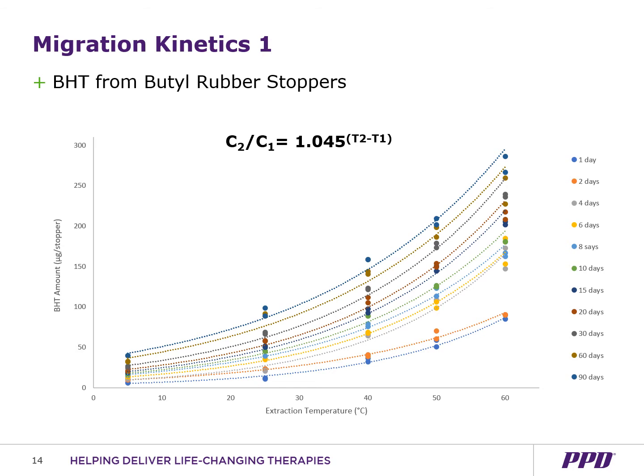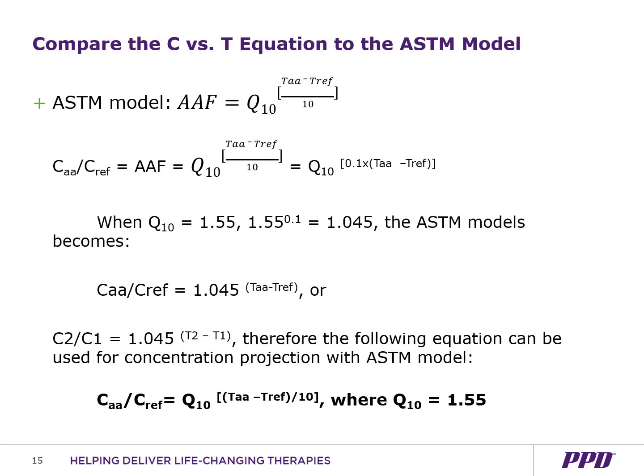We were then able to use the equations generated by each curve, just as we did for the last graph, to figure out an average concentration equation shown on the top, where a projected concentration, or C2, divided by a known concentration, or C1, equals a constant 1.045 raised to the difference in temperature. So we took that constant of 1.045 that we generated based on the average of curve equations generated on the last graph and calculated a Q10 value of 1.55.